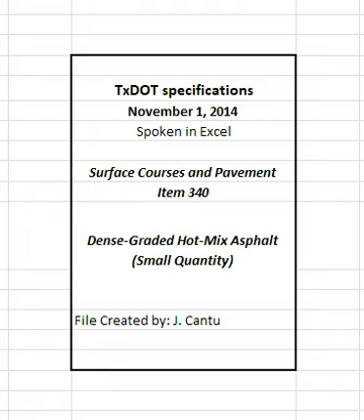4.4 Production Operations. Perform a new trial batch when the plant or plant location is changed. Take corrective action and receive approval to proceed after any production suspension for non-compliance to the specification. Submit a new mix design and perform a new trial batch when the asphalt binder content of any RAP stockpile used in the mix is more than 0.5% higher than the value shown on the mixture design report, or RAS stockpile used in the mix is more than 2% higher than the value shown on the mixture design report.